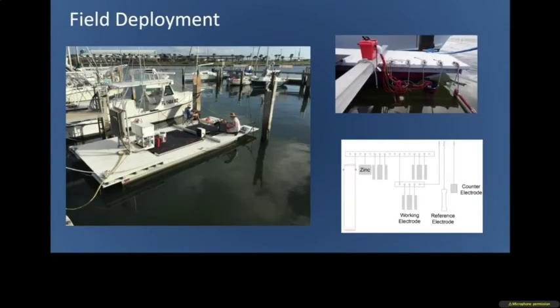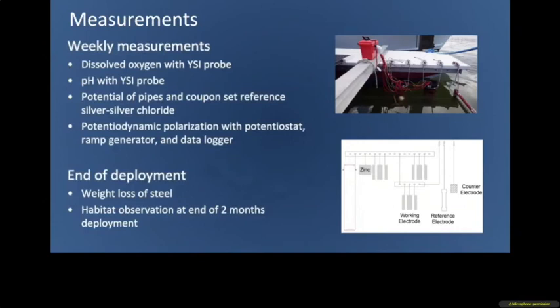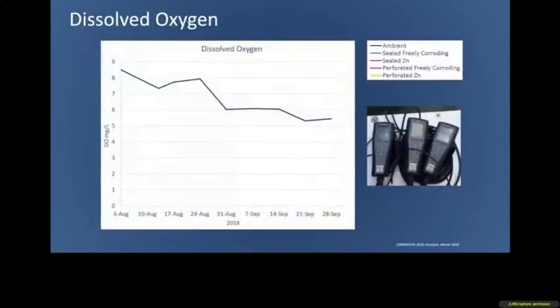And this is a picture of the field deployment, of one of our floating test rafts, and the wiring diagram, which I don't have too much time to go into. Once a week, Monica would go and measure the dissolved oxygen, the pH, the potential of the pipes, and she would also do what we call potentiodynamic polarization. At the end of the deployment, we looked at weight loss, and we looked at the habitat that was created in the different environments for marine life. So I'm only going to present a very limited amount of data which she collected.